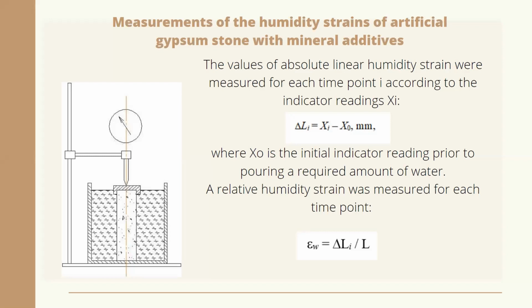Each specimen was inserted vertically into the container and a steel or glass plate laid over it. The indicator of clock type that was clamped in the laboratory holder was connected to it and initial indicator readings were recorded. The container was filled with the water to the level of the upper edge of the specimen, and the indicator readings were taken every 0.25 to 0.5 hours during the first 6 hours. Then they were taken for at least 24 hours. The values of absolute linear humidity strain were measured for each time point according to the indicator readings.